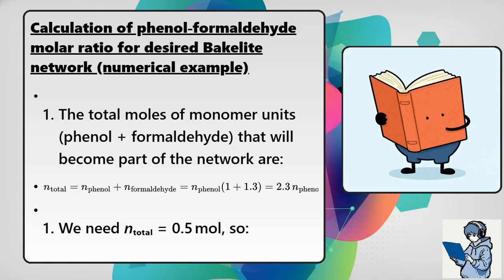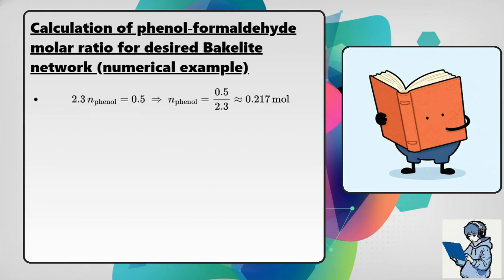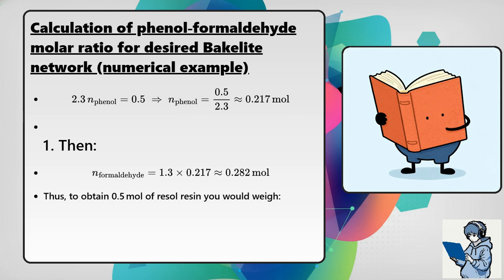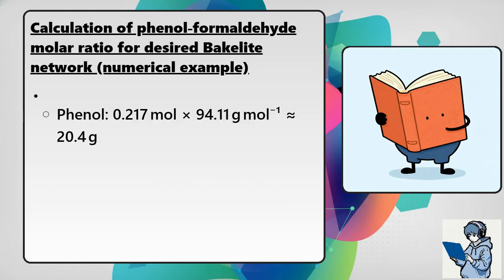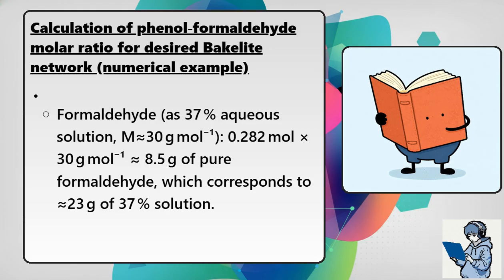Step 4. We need N total equals 0.5 moles, so 2.3 N phenol equals 0.5 implies N phenol equals 0.5 divided by 2.3, approximately 0.217 moles. Step 5 then. N formaldehyde equals 1.3 times 0.217, approximately 0.282 moles. Thus, to obtain 0.5 moles of Resol resin you would weigh phenol: 0.217 moles times 94.11 grams per mole, approximately 20.4 grams. Formaldehyde as 37% aqueous solution, M approximately 30 grams per mole.